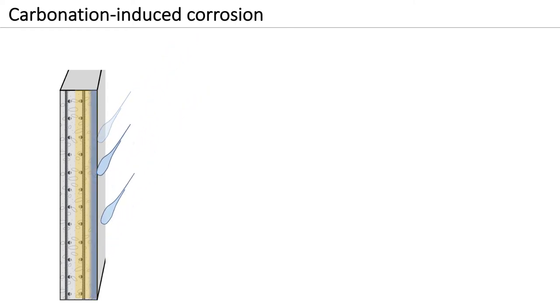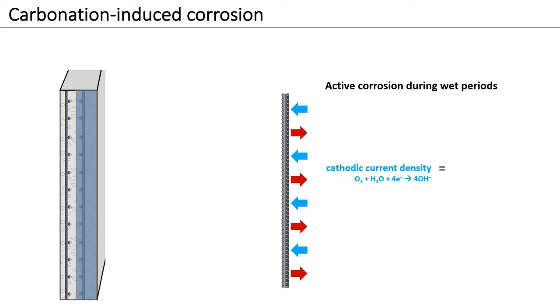In carbonated concrete, the corrosion of the steel is generally uniformly distributed on the steel surface. Cathodic and anodic reactions happen on virtually the same area. This type of corrosion is also referred to as microcell or uniform corrosion.